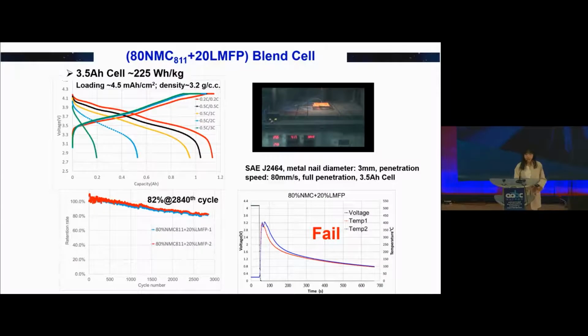And we also successfully developed the 80% NMC with 20% LMFP composite cell, which achieves an energy density of 225 watt-hour per kilogram. However, when using a regular PP or PE separator without ceramic coating, we noticed that the cell did not meet the safety requirement. So we were thinking if there's another alternative measure to enhance the safety of the cell.